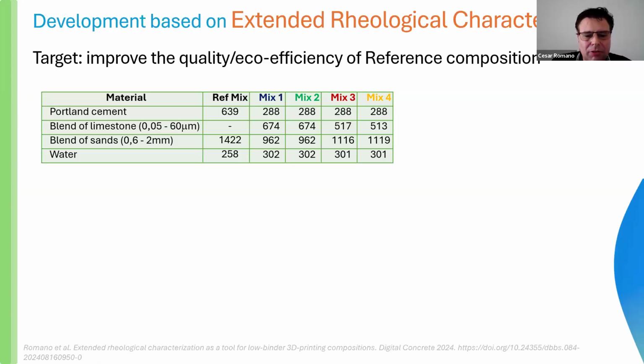When we received our first 3D printer for testing, we had no prior experience with the technique or the equipment. And the machine supplier recommended a reference mixture that, according to them, was already consolidated for printing with that system. This reference I'm showing here. So after receiving training and technical guidance from the company, we began the tests without initially modifying the proposed composition.